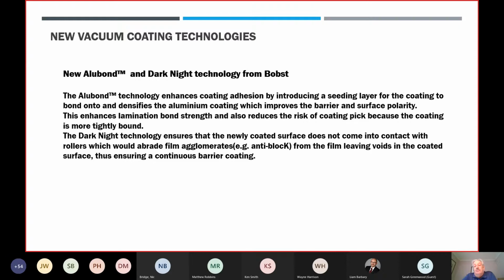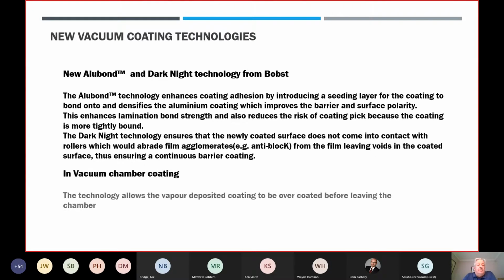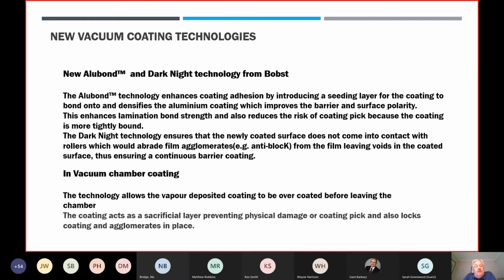Like in a polypropylene film, that would most likely be anti-block, and leaving voids in the coated surface, thus ensuring a continuous barrier of coating. There is another technology for vacuum deposition, and that's in-vacuum chamber coating. To my knowledge, there are only 2 suppliers globally at the moment that have this available to them. And this technology allows the vapor deposited coating to be immediately coated actually inside the vacuum chamber.